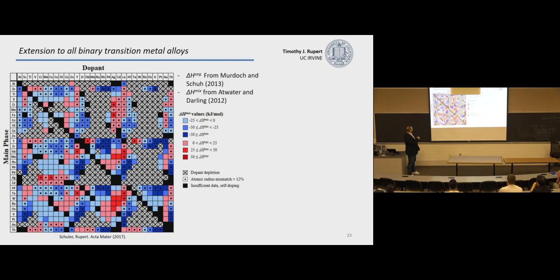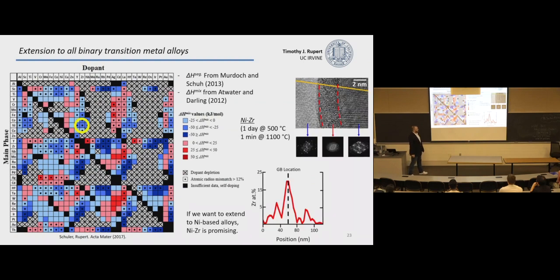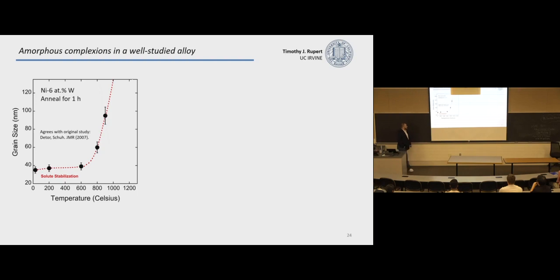So for example, I could say nickel, what works? Nickel zirconium works. Let's go and redo that same experiment. Hey, we found amorphous grain boundaries in nickel now, okay? You can even go and see how we can revisit other types of materials that people have studied to death but didn't see these features. So nickel tungsten, our alloy selection rules suggest would be able to form these amorphous grain boundaries, but people had never seen them before. I actually did my PhD all on this nickel tungsten system.